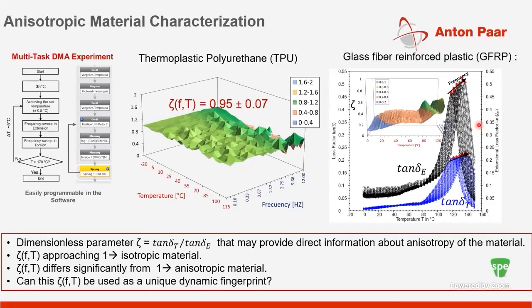So now if you plot the same zeta, which I showed you earlier for TPU, it looks totally different. It deviates strongly from 1, as you can see—it's much lower in this case. So it clearly shows that you can characterize anisotropic materials. Can this zeta be used as a dynamic fingerprint of an anisotropic material?